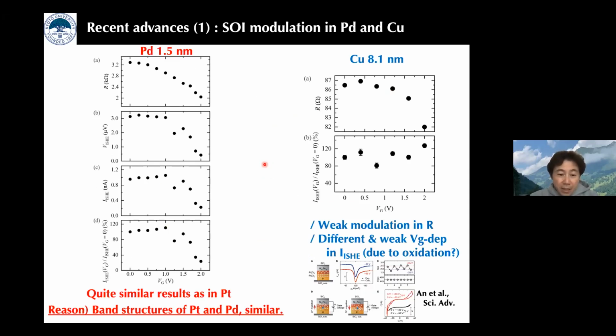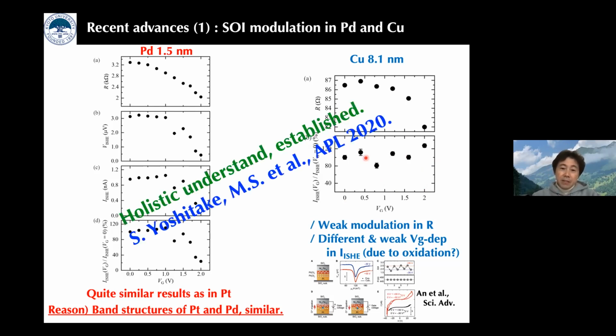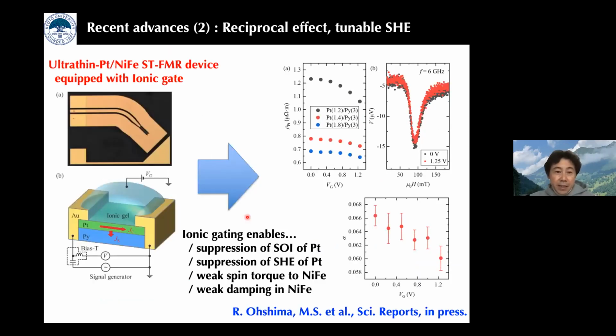After that, we carried out some additional experiments by using palladium ultrathin film and copper thin film. As you may know, the band structures of platinum and palladium are quite similar, and this means the distribution of the density of states of the d electrons around the Fermi level is very similar. And we can expect a similar effect in ultrathin palladium. In fact, as you can see, we can control the inverse spin Hall effect by the gating in ultrathin palladium. And of course, nothing happens in thin copper film because copper is a weak SOI material, and the density of states of d electrons around the Fermi level is almost nothing. So we published this result last year, and this is the latest result about the first topic.